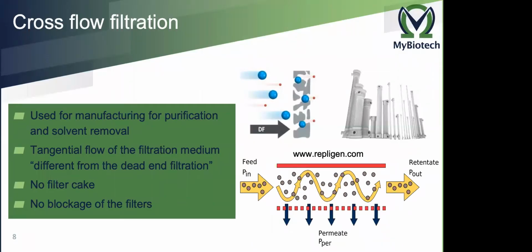Just a couple of pieces of information about cross-flow filtration. That is a technique that we have been using for quite a long time, but basically for manufacturing and for purification or solvent removal. For example, when you prepare nanoparticles by precipitation, you always have an organic solvent in the nanoparticles, and you can remove this organic solvent from the nanoparticle dispersion using cross-flow filtration down to the ppm level. That is the reason that we knew that these filters are able to separate the nanoparticles from any kind of medium. It can be the dissolution medium, but it can be just the medium that the nanoparticles are dispersed in. So we basically modified these filters for use in the dissolution test.